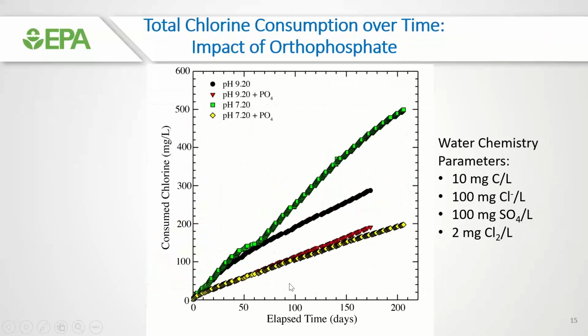This is another way of looking at it, just to show that even for pH 9 and 7, this is the total amount of chlorine consumed over this experiment of 150 to 200 days with orthophosphate and without. So, big benefit.